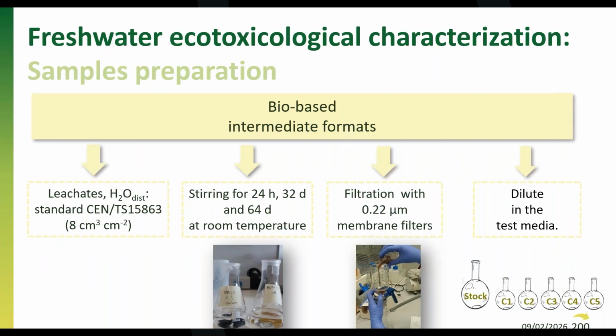Okay, and for the bio-based intermediate formats, the same. We need to produce the leachates in the ratio that is recommended by the standard guideline. And then in this case, for the intermediate formats, the standard guidelines recommend that we should test the toxicity of leachates with different stirring periods. So we tested after 24 hours of stirring, 32 days and 64 days, and this is done at room temperature. Of course, for the bio-based materials, we also need to filtrate these leachates through 0.22 micrometer filters, and then dilute this eluate for the 5 concentrations to be tested in the ecotoxicity assays. Next slide, please.